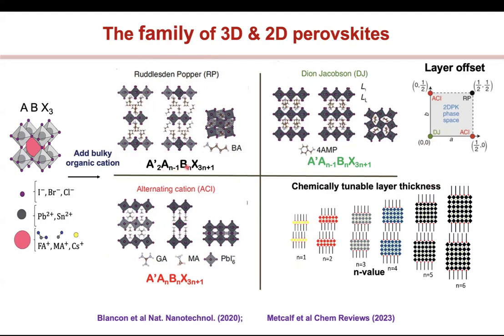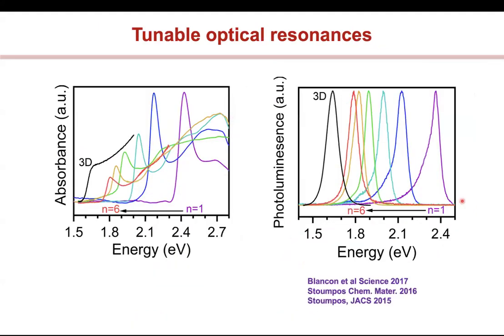So what I call the N number, which is the number of layers that I have, just like you would tune your size in a quantum well or in a quantum dot, I can keep changing. I can control this chemistry very well, and I can change the number of layers. So you can see I can go from N1, 2, 3, all the way to 6. And of course, these are spaced by these organic cations. And obviously, when I do that, what I'm changing is the confinement, right? Quantum confinement in this material. This is a typical particle in a box type picture, N1 to N6.